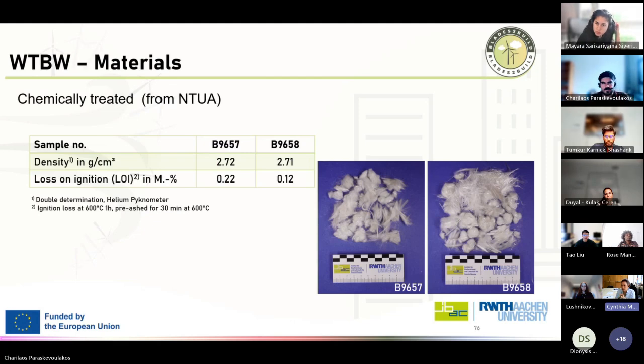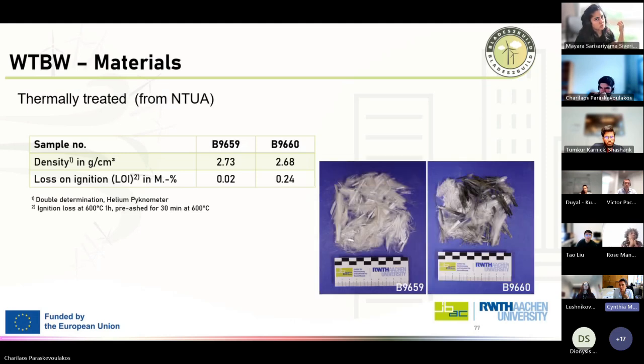So now we see some pictures of how the chemically treated fibers look. These are exactly the chemically treated fibers that were provided by our colleagues from Greece. Also here, different batches deliver minimal differences in the loss on ignition content and actually not even really measurable, more or less the same density. If we go to the next slide, please, then we will see the thermally treated fibers, which were also provided by our colleagues from Greece. Just looking at the pictures, you will see directly the sample 8660 is something black. So it does differ. This is measurable in the loss on ignition content as well.